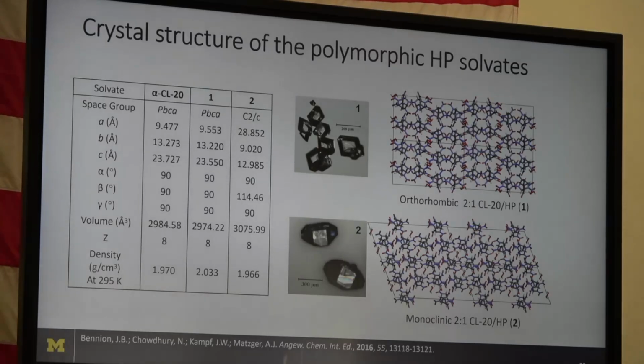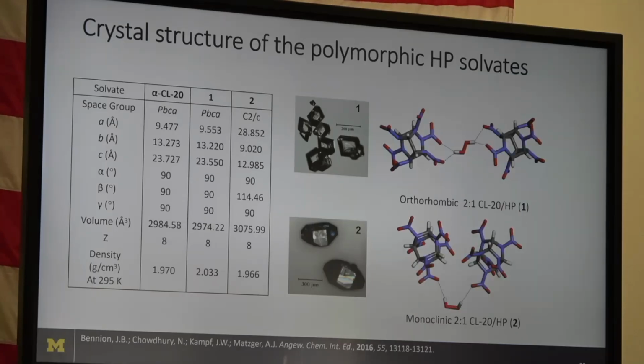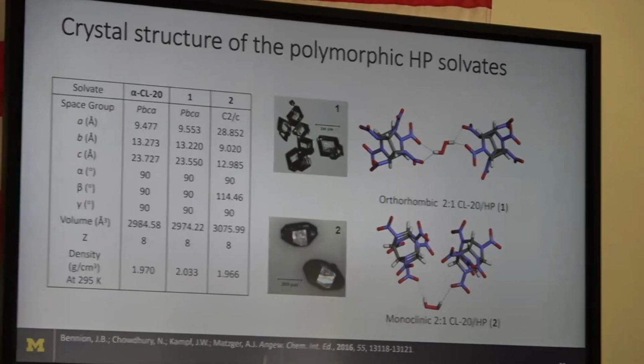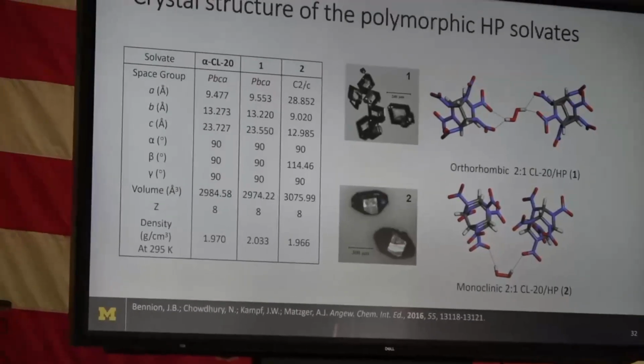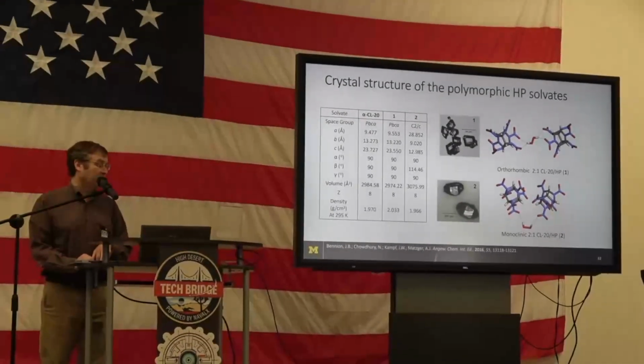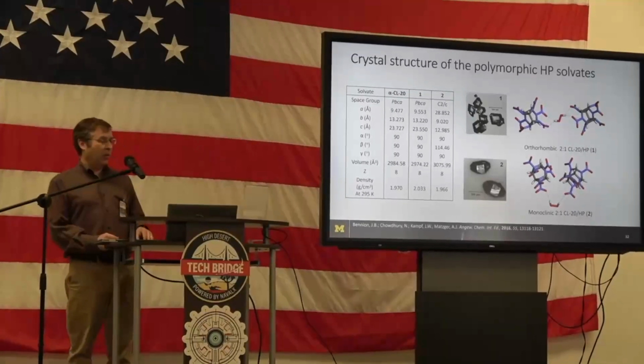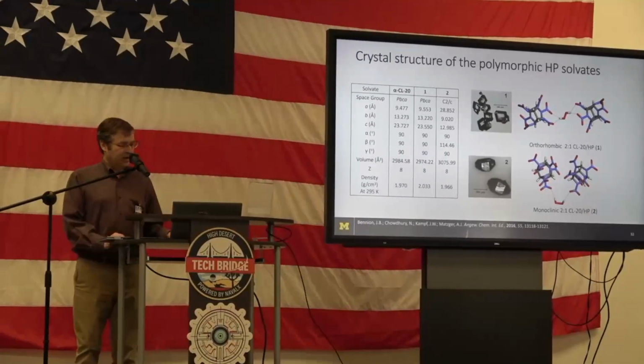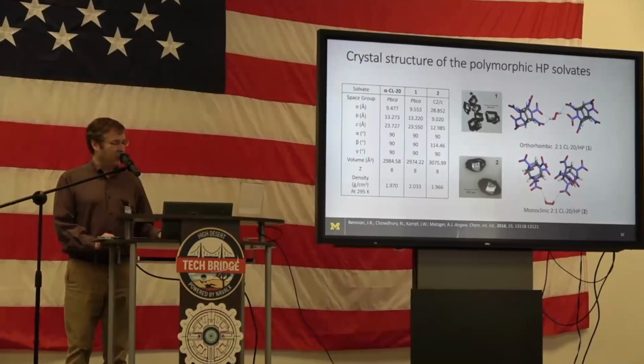And here are crystal structures, and we got more than we wanted. We got 2 polymorphs of the solvate, and one of those has a density of 2.033 at room temperature. The other one also has a pretty respectable density. And if we look at what's going on, there's hydrogen bonding interactions between the nitro group, not the best hydrogen bond acceptors, but peroxide is a pretty good hydrogen bond donor, and so it is willing to make this solvated form.